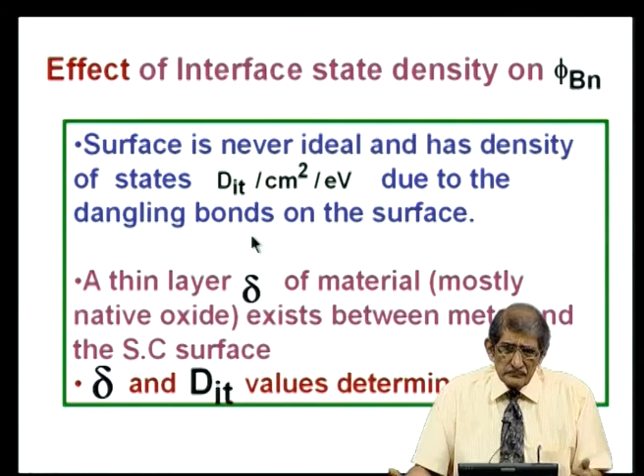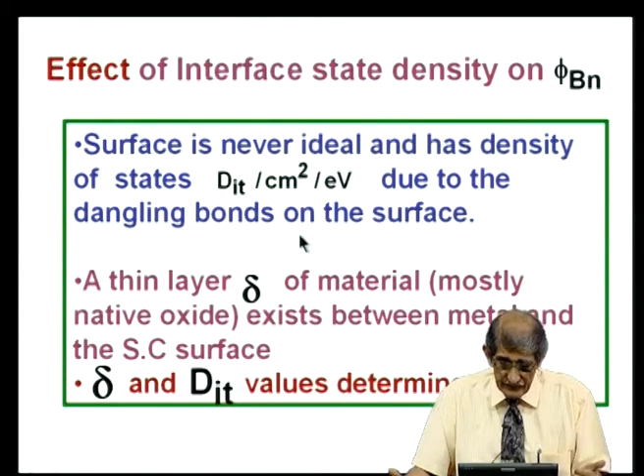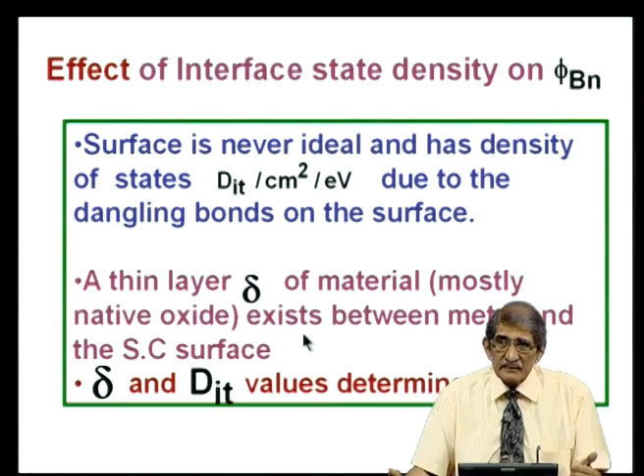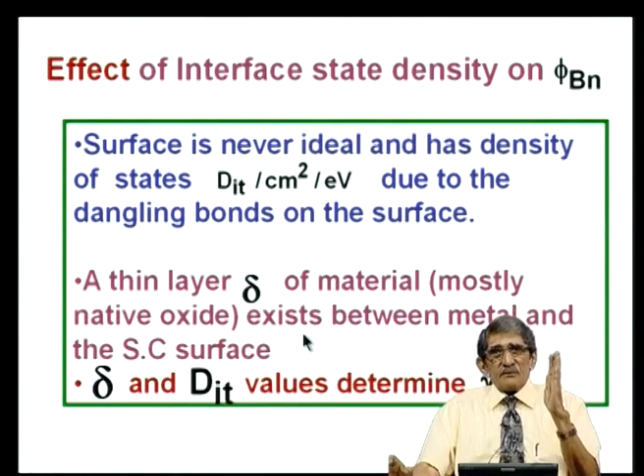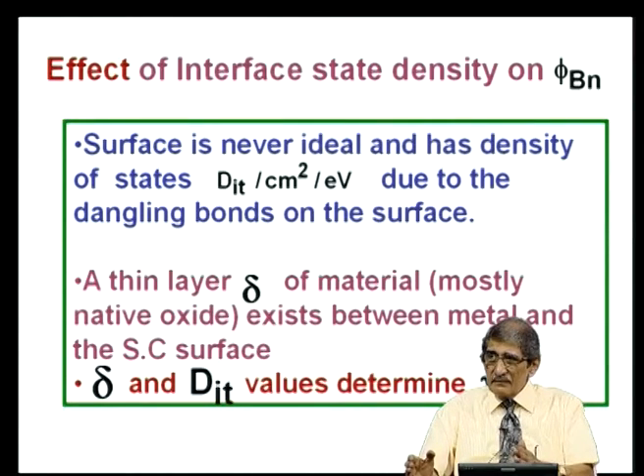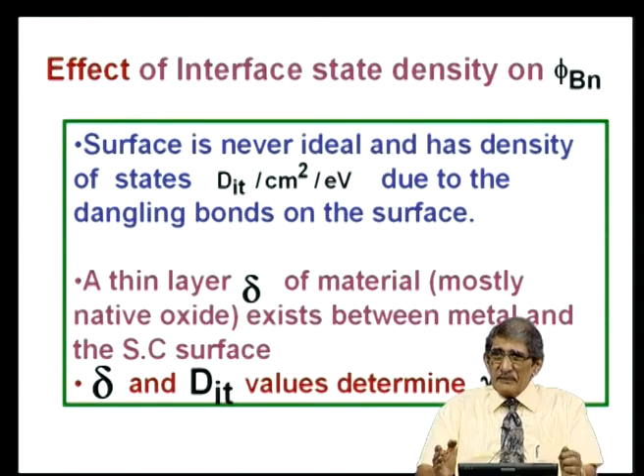Also, there is always a very thin layer of native oxide or some adsorbed layer, mostly native oxide, between the metal and the semiconductor surface. So, if you take a freshly cleaved semiconductor surface and put a metal, it is not directly in contact with the silicon. There is some small gap between them, which is a native oxide or some adsorbed layer, and that we call delta, maybe a nanometer or a fraction of a nanometer, of that order.